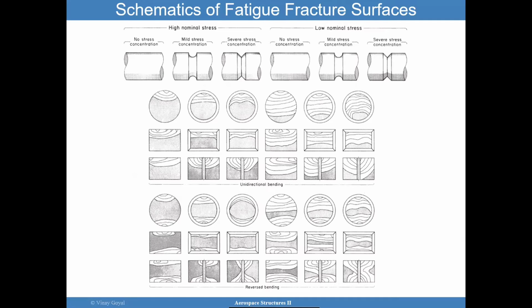If you're looking at unidirectional bending, a bending type situation, I'll just focus on these, and I want you to spend some time thinking about the way this looks here at the bottom. But again, not very different from what I covered on the tensile situation. And if I have reverse bending, then expect two initiation points, one on the top, one on the bottom, if your axis for reverse bending is right here. You can see here that when I go with a lower nominal stress, the beach marks emanate from both ends, and then they cover more area, and then you have this small amount of area left for sudden fracture.